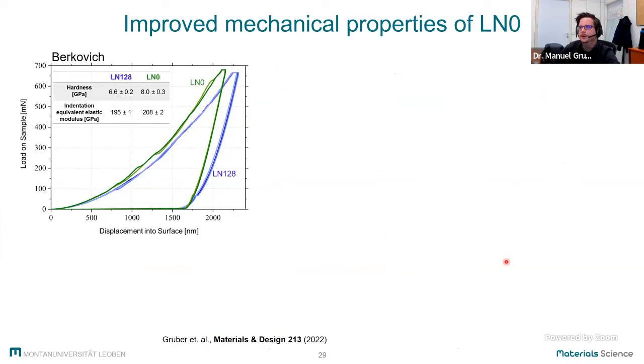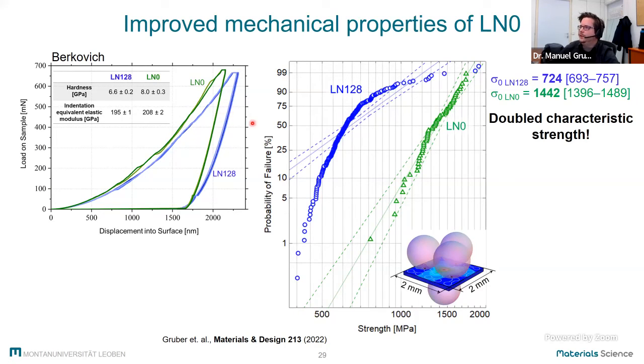And indeed, our Berkovich hardness measurements showed that we get a higher hardness for this LN0 configuration compared to LN128. So a higher hardness, around 20% higher. We again did our biaxial bending tests and could see that the characteristic strength doubles for this configuration. So this is really good news.